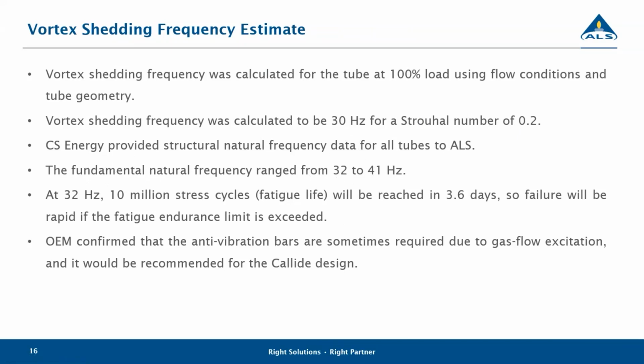So they've also, during operations through a site access door, taken some video imaging of the tubes and clearly seeing that tubes can get excited. So at 32 hertz, if the tube had to be excited enough to cause damaging stress cycles, those stress cycles will ramp up very quickly because it is at a high frequency, and if it's significantly excited, will fail pretty rapidly. So that's what we suspect happened.